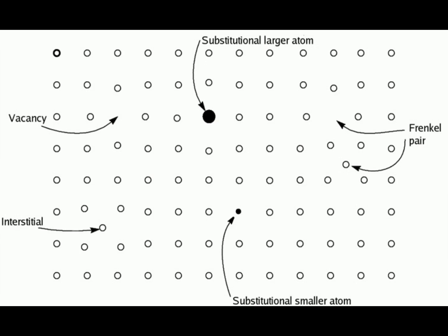Occurrence. Iron oxides. Non-stoichiometry is pervasive for metal oxides, especially when the metal is not in its highest oxidation state. For example, although wustite has an ideal formula FeO, the actual stoichiometry is closer to Fe0.95O. The non-stoichiometry reflects the ease of oxidation of Fe2+ to Fe3+, effectively replacing a small portion of Fe2+ with 2/3 their number of Fe3+. Thus, for every 3 missing Fe2+ ions, the crystal contains 2 Fe3+ ions to balance the charge.